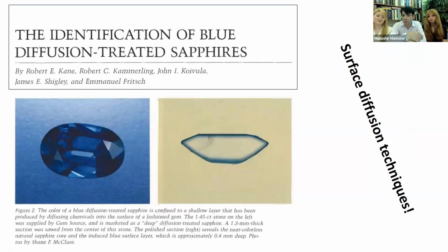And then there are, of course, the surface diffusions, the most notorious of them all, I would say, where you can get a thin film of titanium diffused into the sapphire when the sapphire by itself does not have enough rutile or enough coloring agents where you can just put them in by diffusion. These treatments take very long, so they usually require 1 month of heat treatment at about 1700 Celsius. It's not easy, but people go to extremes to do these treatments, and they usually do it on already shaped gems, and then they just do the final polishing once the treatment is done. So these are also very simple to identify. You have facet junction colorers, and they're so famous that I think they do not require much explanation.